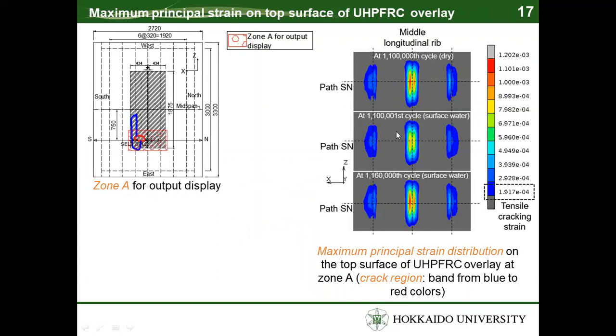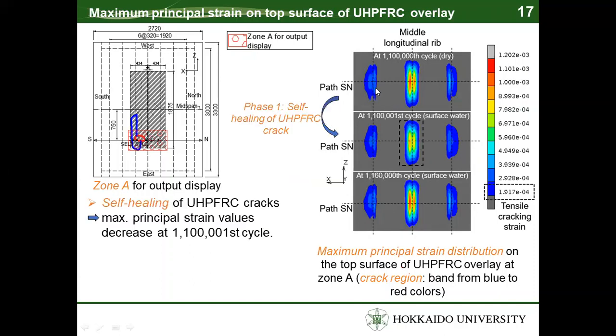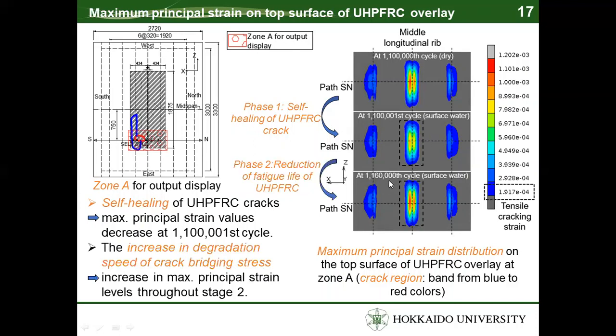This figure shows the maximum principal strain distribution on the top surface of UHPFRC overlay S1A. The cracked regions are shown by a scale from blue to red color. In phase 1, due to the self-healing of UHPFRC cracks, the maximum principal strain value decreased, as shown in this figure. And then, under moving wheel loading, due to the reduction of the fatigue life of UHPFRC, an increase in maximum principal strain level could be obtained throughout phase 2, as shown in this figure.